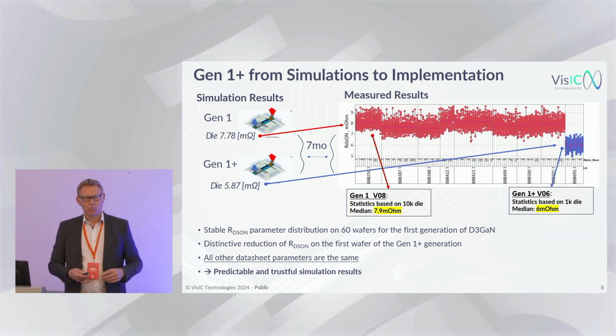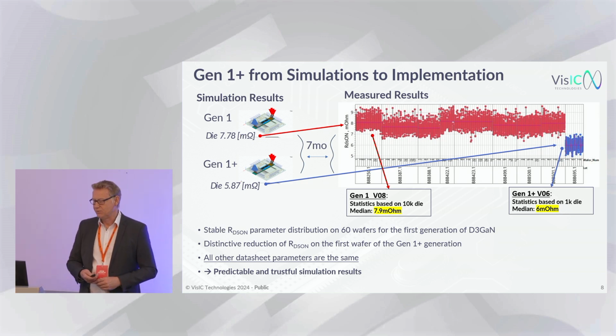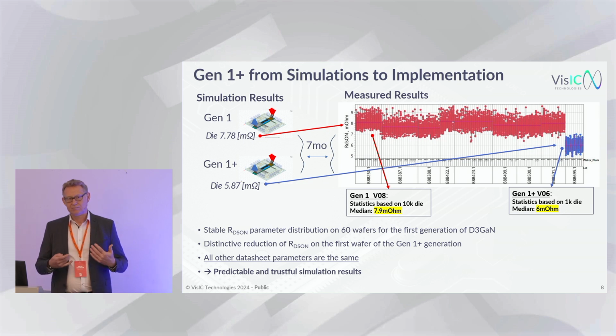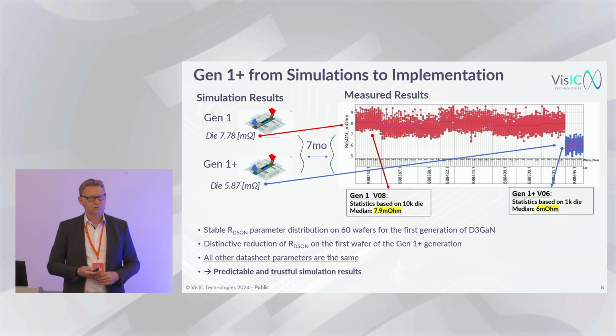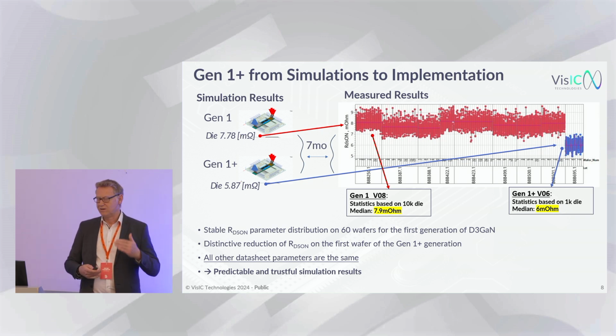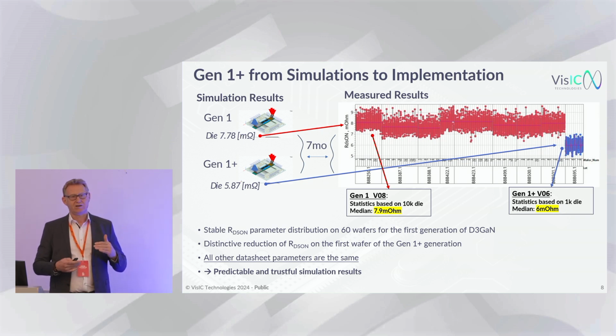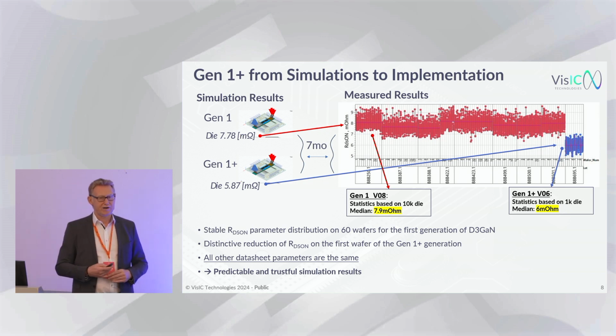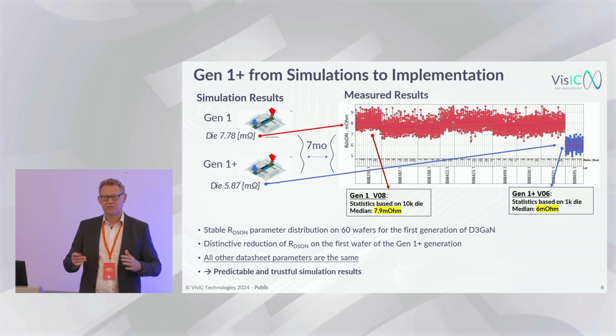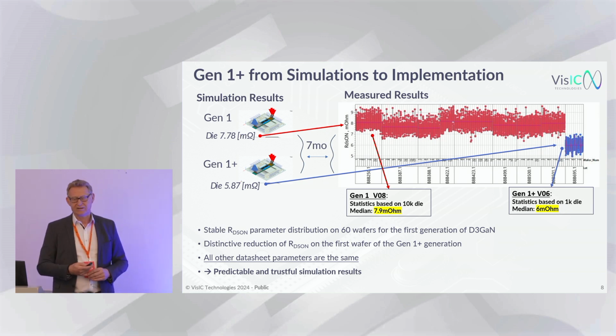So our generation 1 was a 7.78 milliohm in simulation, and when we manufactured the device over the last 2-3 years, we were really around this kind of boundary in a very narrow area. So we have plus minus 10-15% spread, so not like in silicon carbide where you have a 20-30% spread of RDS on, so we will have a very narrow spread.